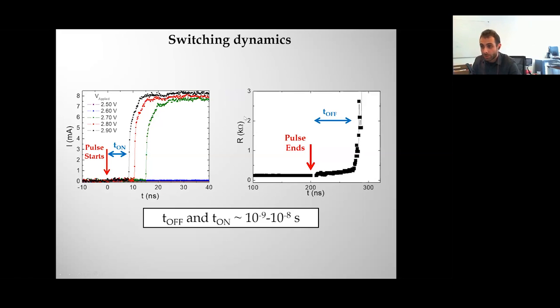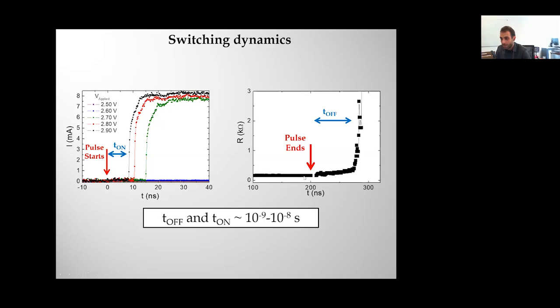So we measured that. This is resistance as a function of time. The pulse is applied here, and at 200 nanoseconds we stop the pulse, and you can see that the resistance of the material remains low for a few tens of nanoseconds until the device cools down, and then it shoots up because the device becomes insulating. So you can see that both the insulator to metal and metal to insulator transitions happen on a time scale of nanoseconds to tens of nanoseconds.